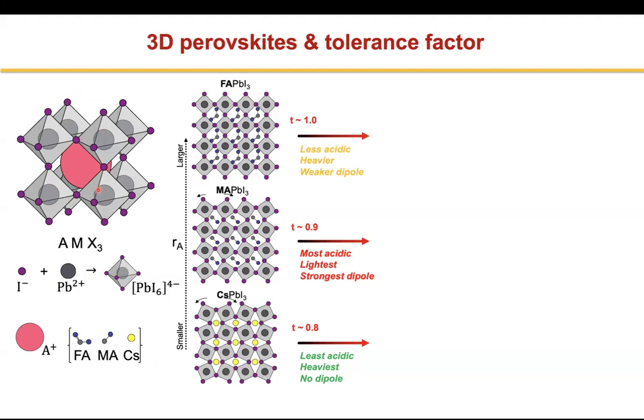Now, if I take the ratio of these ionic radii, it gives me a certain value, and that value is known as the tolerance factor. It's called the tolerance factor because it tells me whether I have made a perovskite successfully. So if I put these three cations and make the perovskite, there are three types of different perovskites I could make. One is formamidinium, FA, which is my cage cation here. It's the monovalent cation, and I form essentially this type of structure. And it has a tolerance factor of 1, which is right on the edge.